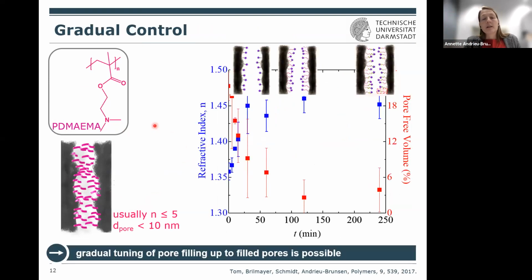And another analysis method is using ellipsometry. Ellipsometry gives you the refractive index and the film thickness of such a thin film on a silicon wafer. And here you see plotted the refractive index and the pore-free volume, which you can extract from the refractive index, because if you polymerize, as indicated here, you fill the free pore space by polymer. Polymer has a certain refractive index, air has a certain refractive index, so you increase the refractive index. And from this, you can deduce the free pore volume or the pore filling degree from the refractive index values. And this corresponds to IR. You see that with polymerization time, you fill the pores basically. And you can reach fairly high pore filling degrees.